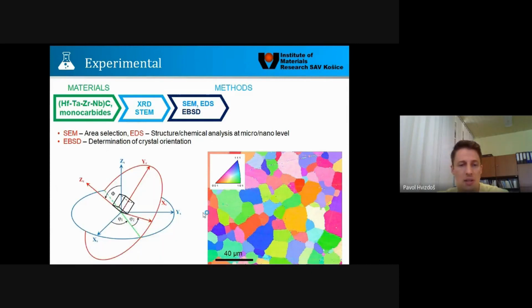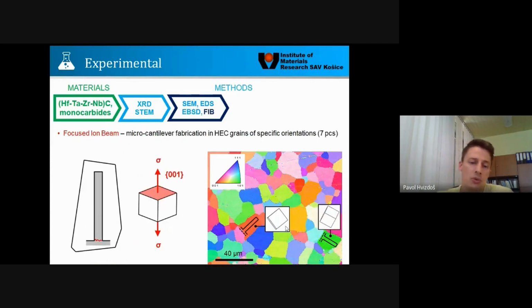And as you can see on the left side, we have a cubic structure. So maybe I forgot to mention that that kind of high entropy carbide possesses the same crystal structure that the original base monocarbide had. It is a cubic phase, cubic symmetry, and as you can see on the right hand side, there are different grains with different orientations, and from those maps we selected specific crystallographic orientations from which we prepared different micro-cantilevers.